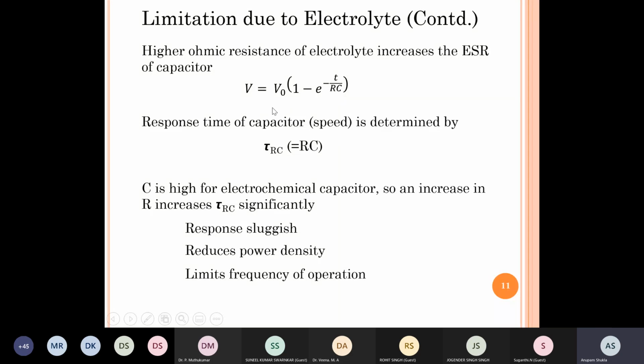If you recall your school book, the rate at which the voltage will drop depends upon the initial voltage times 1 minus e raised to the power minus t over RC. So how fast the voltage goes down is essentially a measure of how fast the current or power is being supplied, and that is determined by what is known as the RC time constant, or tau RC. So the response time of a capacitor depends on this parameter, the resistance, which is ESR, times the capacitance.